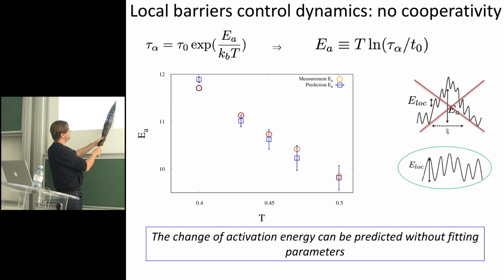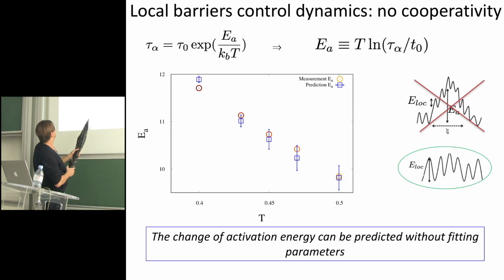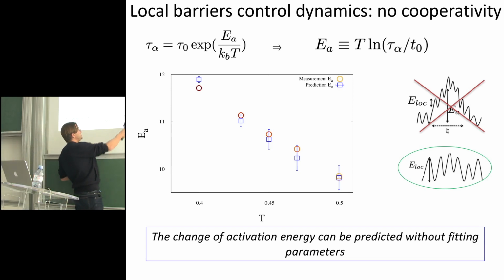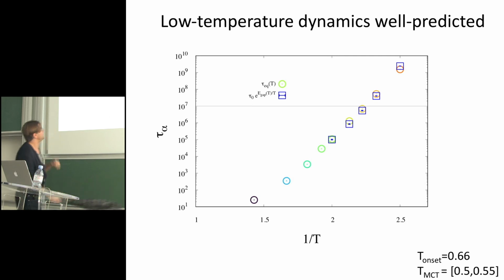Here we have an offset that we don't control. So this point here, you should not be impressed because we fit the two to be the same. But what we really do, which I think is rather remarkable, is that we can predict the change of activation energy without any fitting parameters. So we see strictly no trace of cooperative effects, at least in those liquids, which are the typical liquids that people study numerically. It's the same as saying that we can predict the dynamics as you cool down the system.